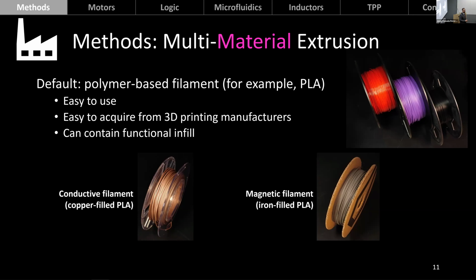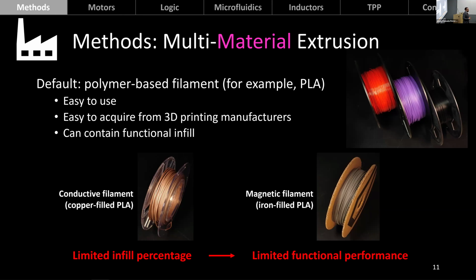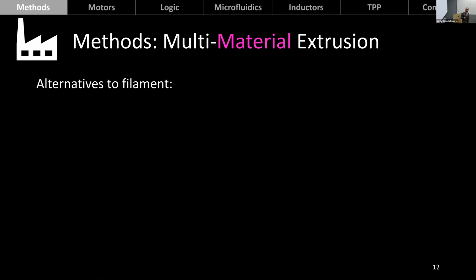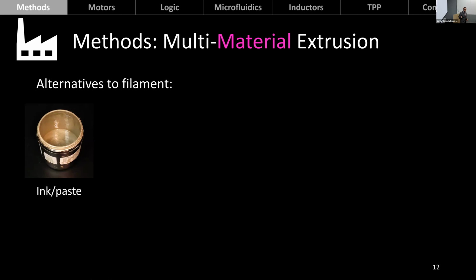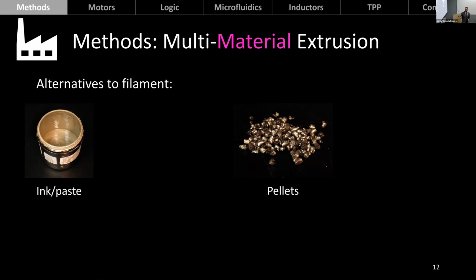So embedding functional materials into these filaments allows us to have performing materials. Now, there is an issue with this, which is that the infill percentage that we can embed into these filaments is limited. And it is limited because if we go past that percentage, then the filament becomes unprintable. So we can't really use it. And that means that there is a limit to the functionality that we can achieve with these materials. But there are alternatives to these filaments. For example, there's ink or paste, and there are also pellets.